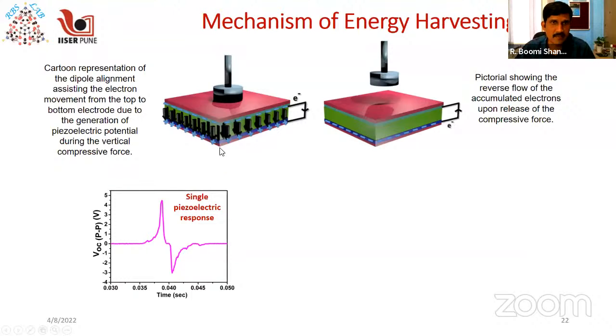So what happens in the system is when you hit the molecule with an external stress, a piezo potential is generated at this particular surface, which allows the negatively charged electrons to be produced at the interfaces. Because of the higher electronic cloud, these electrons now pass through the material to the opposite electrode, which is positively charged. So there is a movement of electrons from top to bottom while you are hitting the composite material, which gives rise to a signal in the positive direction. The moment you withdraw the force, the piezo potential is removed from this surface. The electrons now have to go back in the opposite direction, which will generate a signal in the opposite direction.